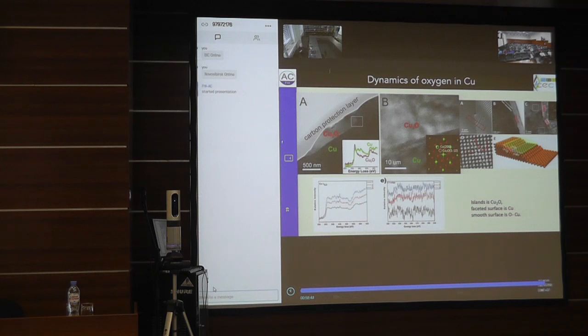And this dynamical situation here was mimicked by hydrogen plus oxygen, but we adjusted the chemical potential such that it is the same as you would have in methanol synthesis. We did not use the methanol synthesis reaction conditions because we wanted to avoid the contamination that we get when there's methanol adsorbed, which creates a lot of additional difficulties when you do the material analysis.